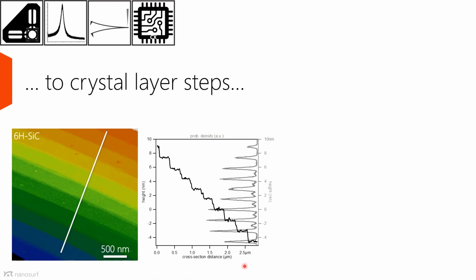And if you also do a height histogram, that's what you see here in gray, you see basically the counts of pixels at a certain height as a function of the height. This also indicates there's a clear 1.5 nanometer spacing between these large terraces. And in the image you can sometimes see some smaller areas which have an in-between height of 0.75 nanometers between each terrace.